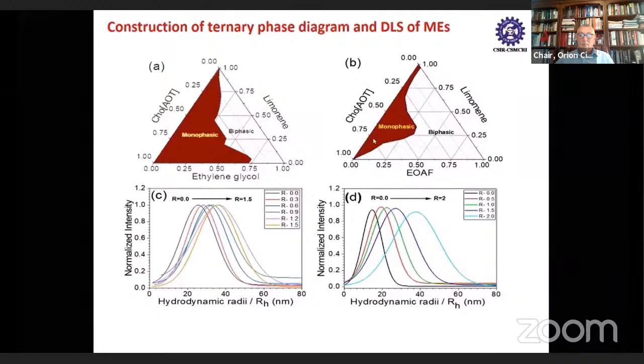So very robust microemulsions of ionic liquids in ionic liquid systems were constructed. The droplet size in the microemulsions, in the case of ethylene glycol, ranges from 10 nanometer to 40 nanometer hydrodynamic radii, and in the case of hydroxyethyl ammonium formate, the droplets were a little smaller. The size of the droplet increased with the increase in R value in both the cases.